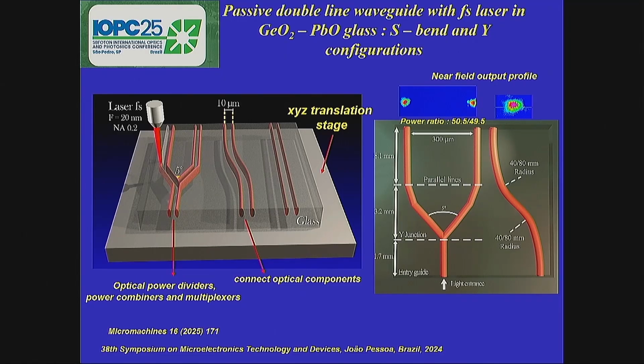In this case, we observed that below 40 micrometers radius, we observed higher propagation losses, so we did not use it. And above 300 micrometers, we did not observe this homogeneity in terms of the light propagation between the two arms. For example, for 600 micrometers, instead of having 49 here, we had something around 46. And this ratio, in fact, gives us the information of the uniformity between these two arms.